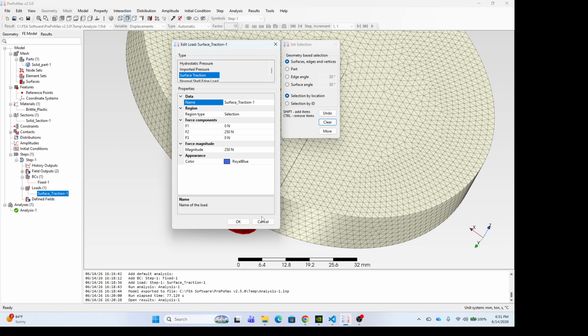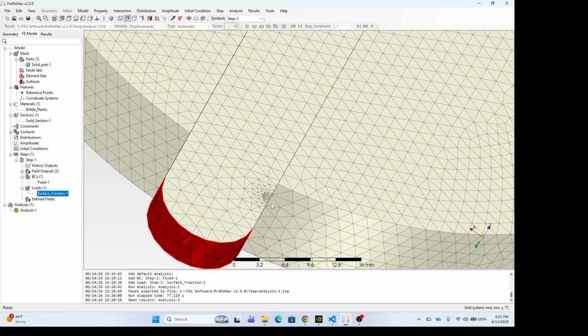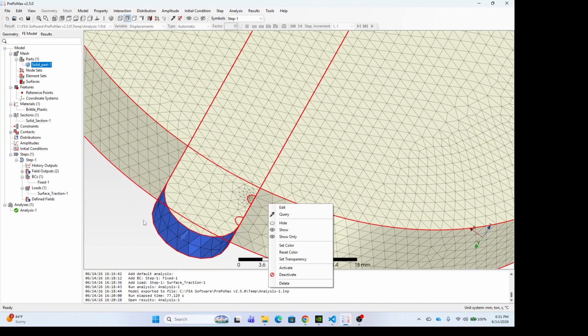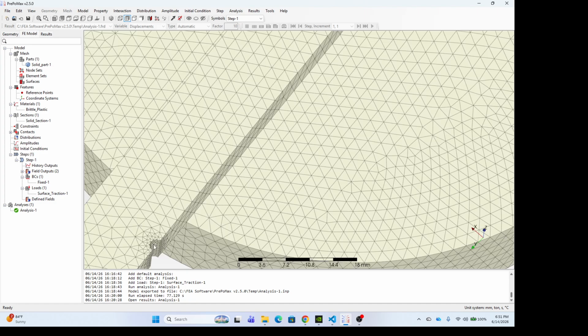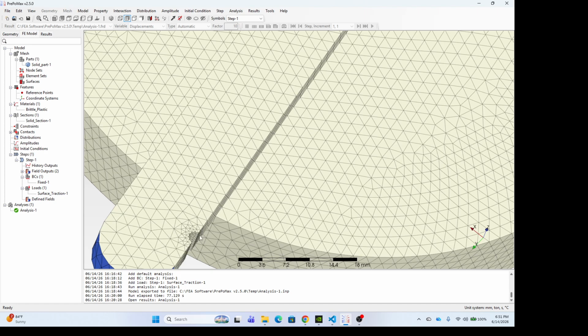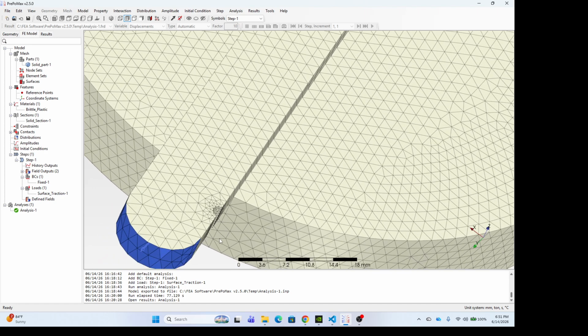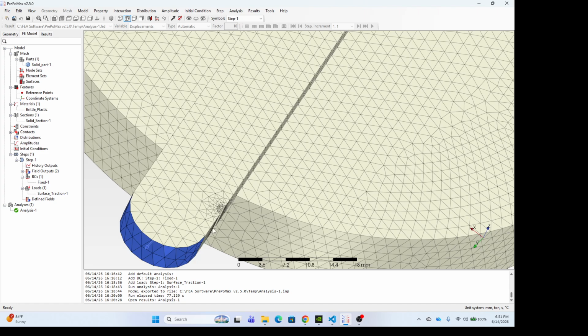So typically, right from the model right now, I would most definitely have to increase the notch size. As you can see here, the gap is, I think, around 0.08 centimeters in diameter. So this would definitely have to increase in size. And so the global stress distributed across the tamper ribbon peaked at just 18.18 megapascals. From the looks of it, the best solution is to increase the size of the notch I created at the side of the plastic seal.